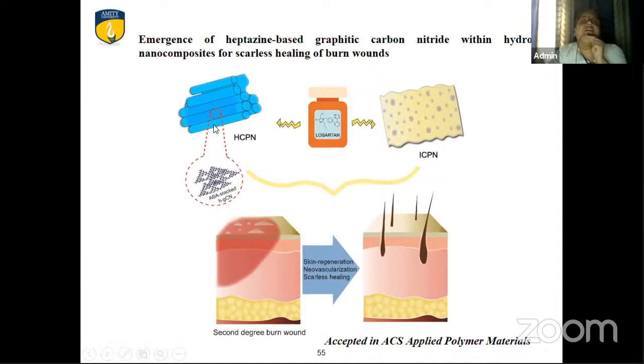nitrides, because here the carbon nanosheets we are using as a filler, not graphene quantum dots, and the carbon nanosheets are melamine doped. Melamine has triazine molecules, and these triazine molecules, because of nano confinement with the help of block copolymers, give rise to the emergence of heptazine-based graphitic carbon nitrides. This is the first report that we got this graphitic carbon nitride at 40 ± 1 degrees centigrade with the help of polymers, with the monomers guiding.